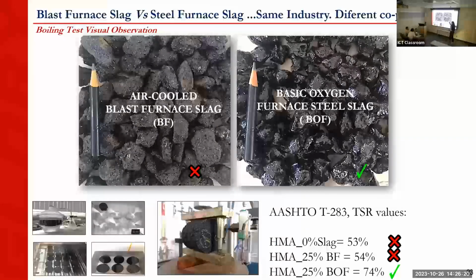Very empirical test, but it gives us this initial insight. When we took those slags and used them to produce asphalt concrete in a moisture damage test, when I replaced natural aggregates by BF slag, the TSR value, I don't know if some of you may be familiar with moisture damage tests, was 54%, which is low. We expect at least 70%.